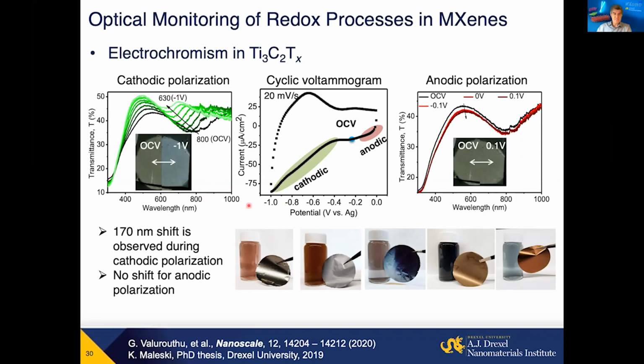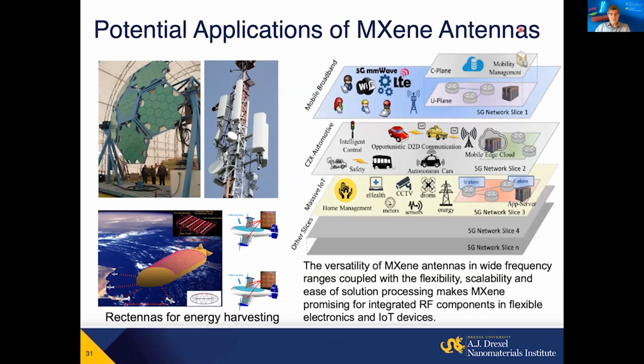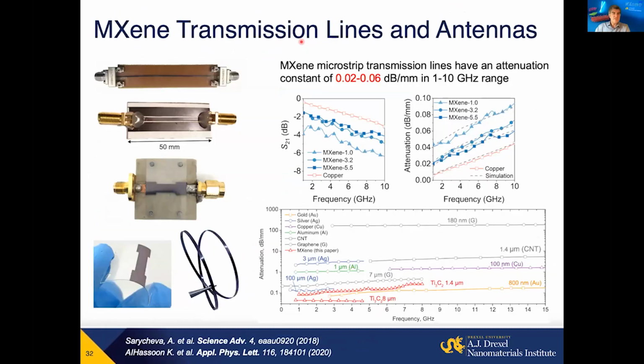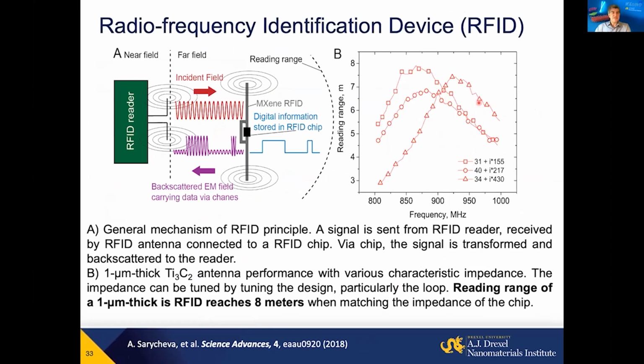And different MXenes, as you can see here, have very different colors. So those are just 5 different MXene foils having different colors, and in solution, they will have complementing color. As I mentioned, those are plasmon colors in these materials. And we can use them because of their conductivity and two-dimensionality for communication in antennas with very low attenuation, lower than some metals, and make again printable antennas, also even transparent antennas. Or we can print RFID tags. And of course, for Internet of Things, having 5G patch antennas, having RFID tags, and being able to print them from just aqueous solution onto pretty much every surface is of great practical interest here.